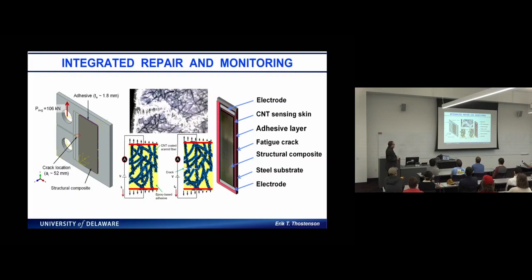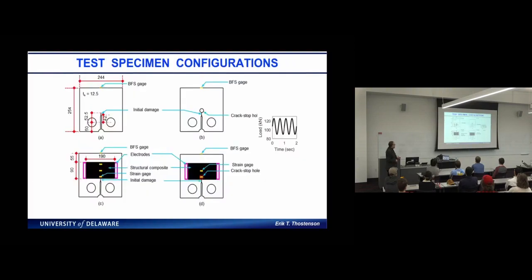So we've added our structural reinforcement, and because our sensor is very thin, we can slip it in that range. And this is just showing as the crack grows, even though the composite is not cracking, that crack will still grow under the composite. But we've designed the strain to failure of this sensor such that it fragments as that crack grows. So we have this, what we call our sensing skin that's integrated at the bond between the composite and the steel. So these are just some different configurations.